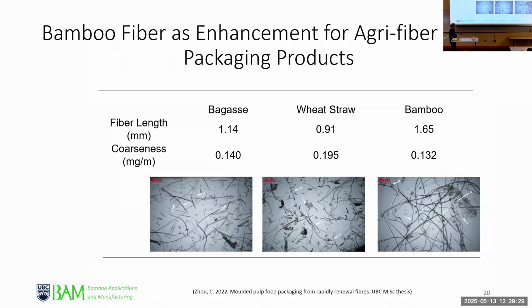You can see the bamboo fiber is much longer and the coarseness is lower. Coarseness is the thickness of the cell wall, which is thinner. The thinner wall, when it comes to making these products, can easily collapse and increase the bonding or the performance. And the longer fiber helps to create more network and stress transfer for the performance of the product. So in both cases, bamboo has an advantage.